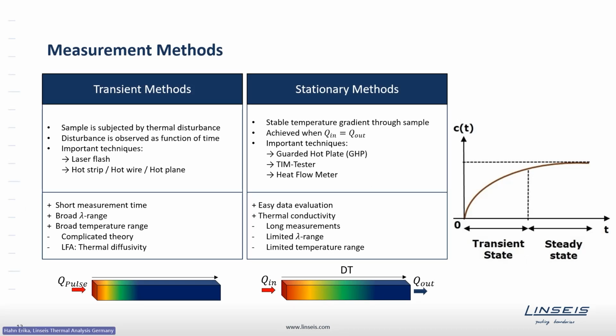Basically, the measurement methods for thermal conductivity or thermal diffusivity measurements can be grouped into two classes. On the one hand, we have the transient methods, where the sample is subjected to a thermal disturbance, and this disturbance is observed as a function of time. On the other hand, we have the stationary methods, where also a thermal disturbance is brought into the material, but we wait until a stable temperature gradient is established through the sample. So this is also seen here.